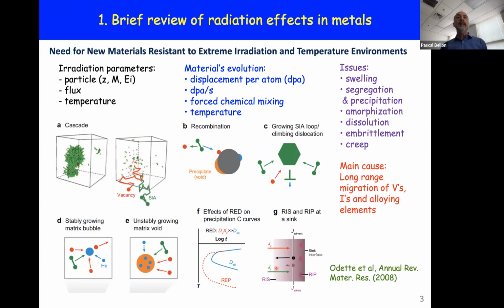And in some cases, these point defect fluxes may couple with solute fluxes, leading to radiation-induced segregation and in some cases precipitation. You may see from this slide here that the main cause of a lot of these types of damage is the long-range migration of vacancies and interstitials, and sometimes alloying elements.